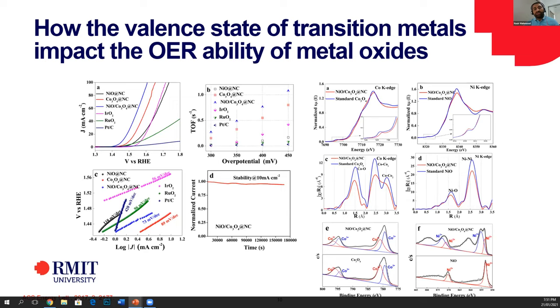So that is giving us a more efficient oxygen evolution reaction. And if you look at that, we are doing it very, very close to what is ideally required, at very low overpotentials, and it is very stable. But what's the challenge with such a catalyst? How do we industrialize and commercialize this product?